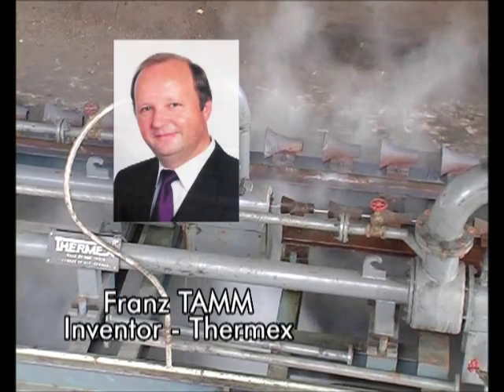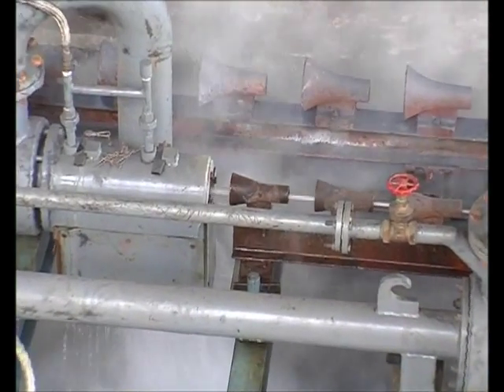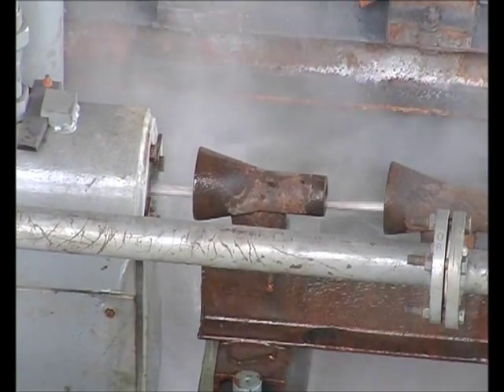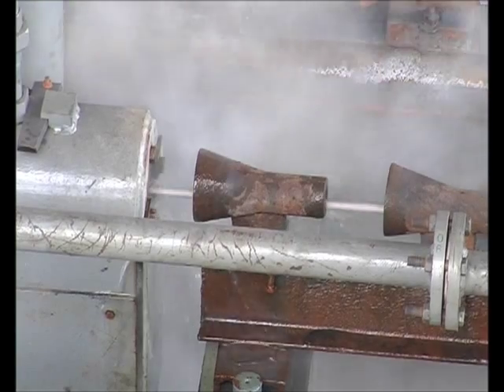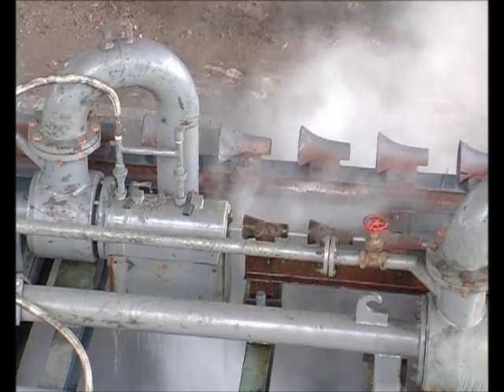Thermex is a quenching and self-tempering process that was developed in Germany specifically to meet the global demand for low-cost rebars with a 500 megapascal yield strength and high ductility. It received global acceptance immediately on introduction because it fully satisfied the needs of civil engineers without addition of costly alloy elements in steel.